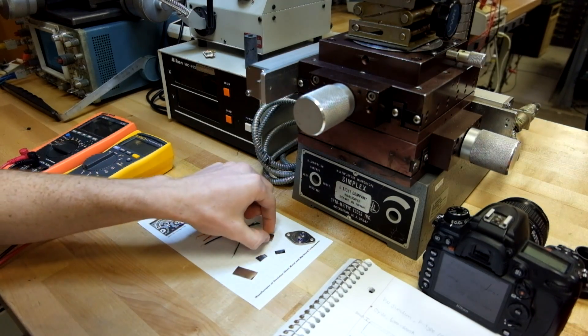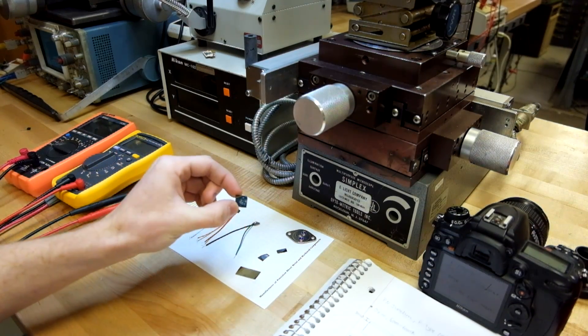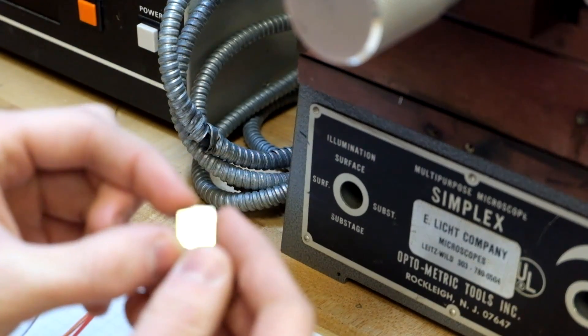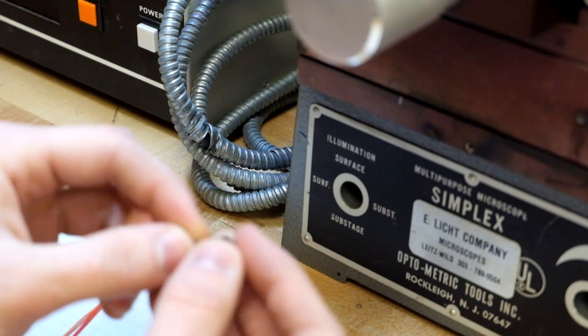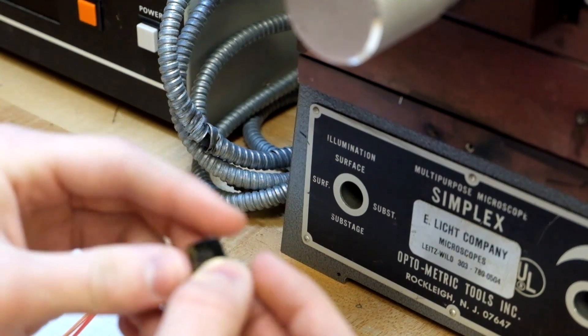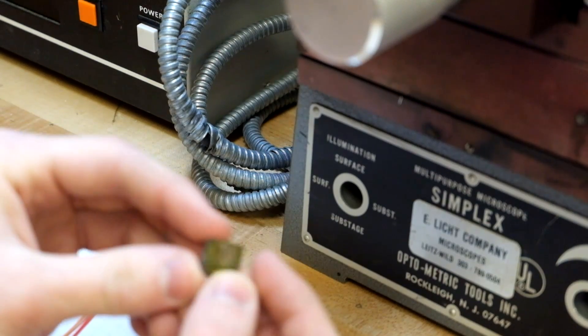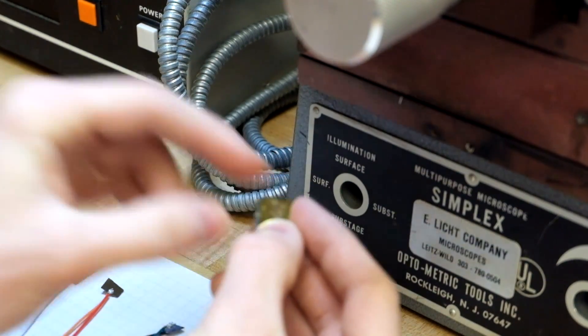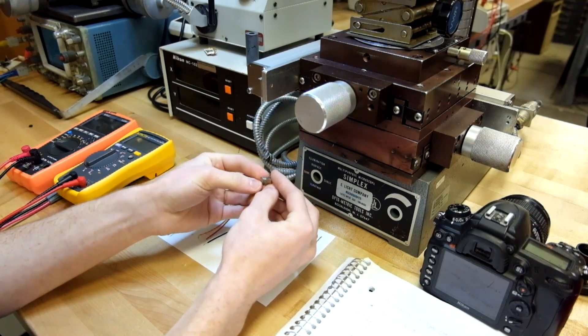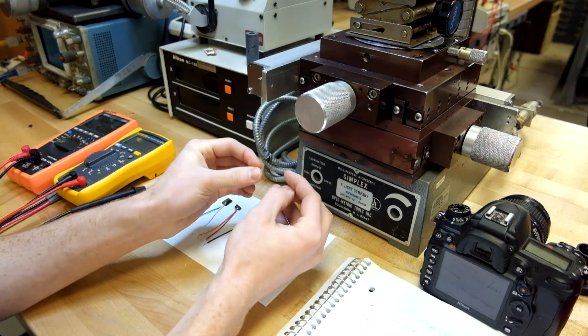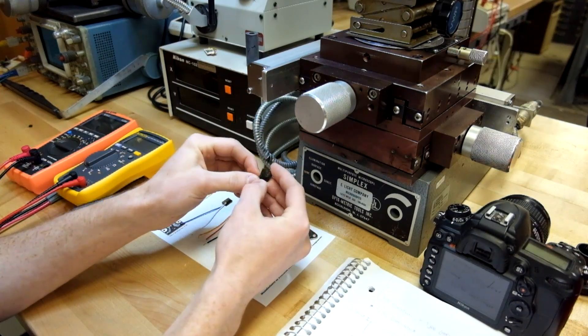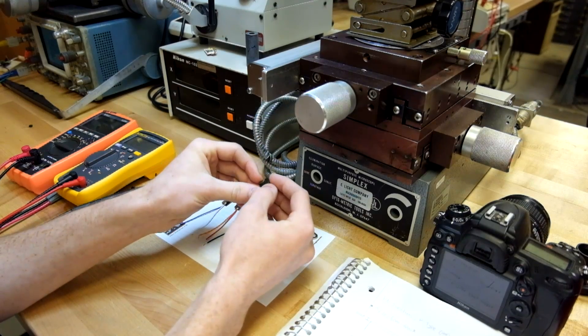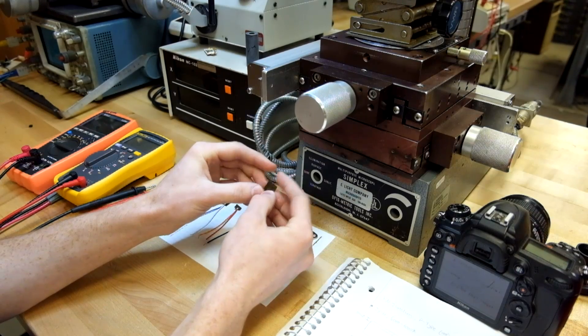The last thing I'm going to show you is kind of a funny solar cell. This one here has a little bit of a yellow tint to it, and I actually created this one by taking a p-type wafer. I didn't grow any silicon dioxide onto it, but I did my doping using Coca-Cola. I actually used Pepsi Throwback because the third ingredient on it is phosphoric acid, and I thought there might be enough of it to successfully dope a wafer, and there was. I chose to use the Pepsi Throwback version because it has natural sugar in it, and I thought that the newly lab-synthesized sweetener sugar molecules would get in the way of all the diffusion and stuff, so just to eliminate that variable, I decided to go with the Throwback version of this soda, and I spin-coated it on here.